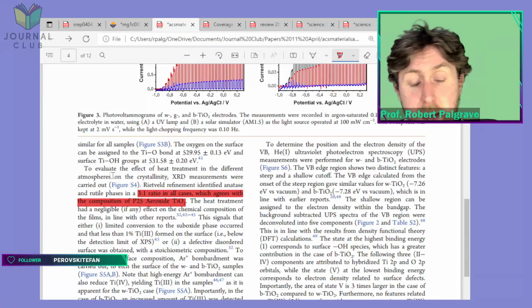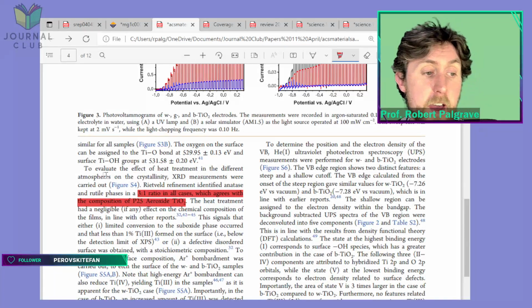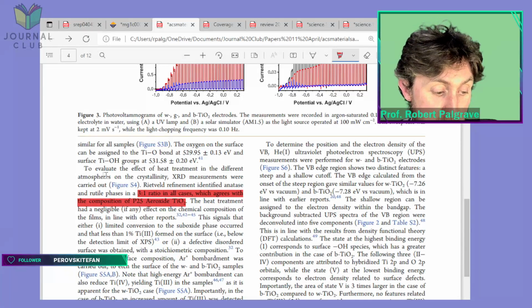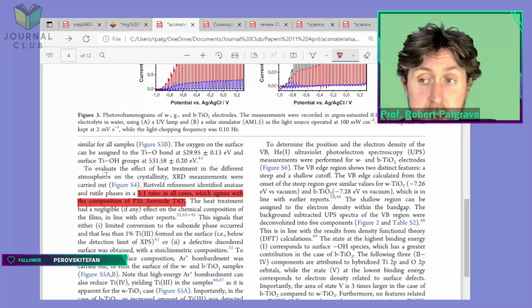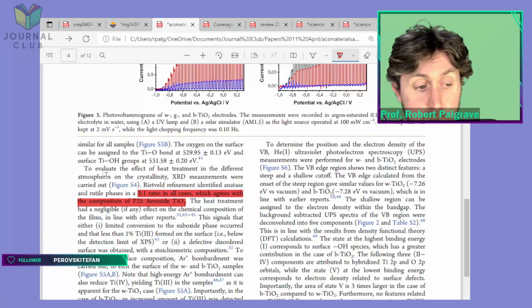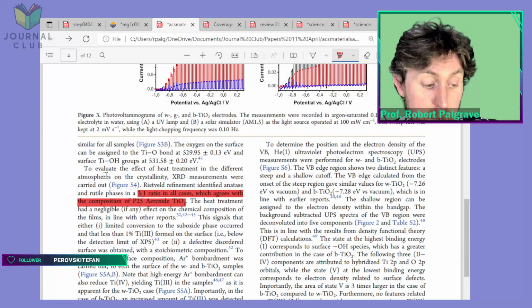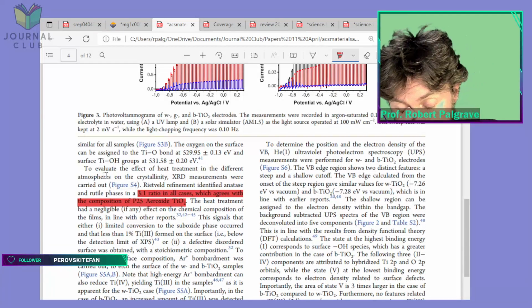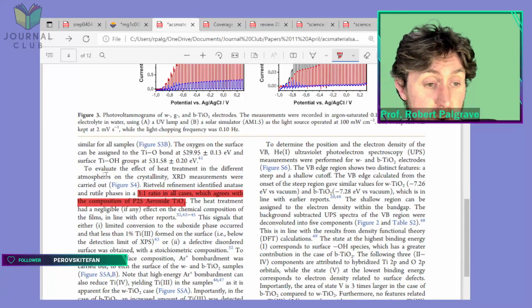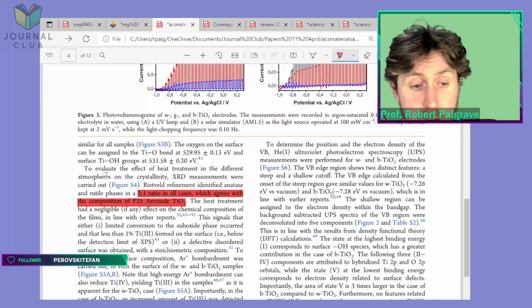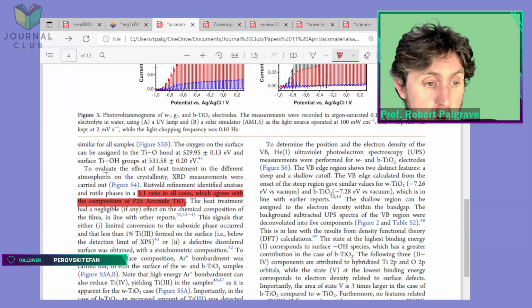So they measured the XRD, it tells you about the crystal structure. They got an XRD pattern, which contained peaks from the rutile and the anatase, and they used this method of Rietveld refinement to build a model of a certain amount of anatase, a certain amount of rutile, and then they changed their model until it matched up well with the observed experimental XRD pattern. Rietveld refinement, very, very powerful technique for quantitatively analysing powder XRD. Really, really universally used in materials science, materials chemistry,